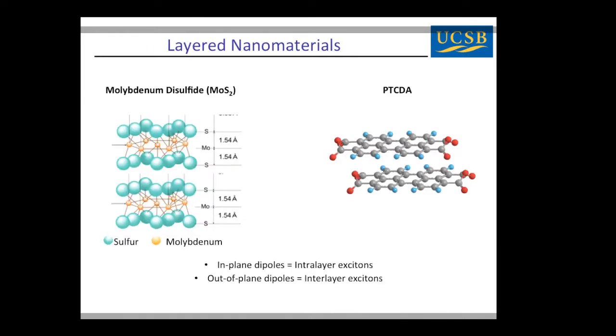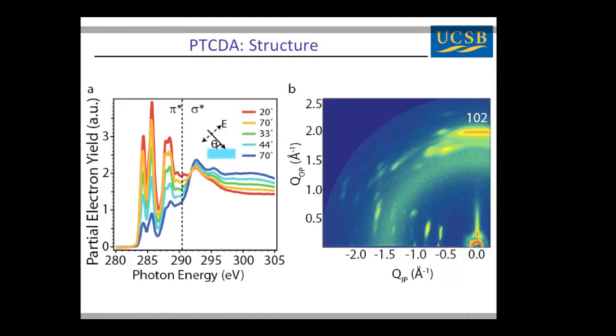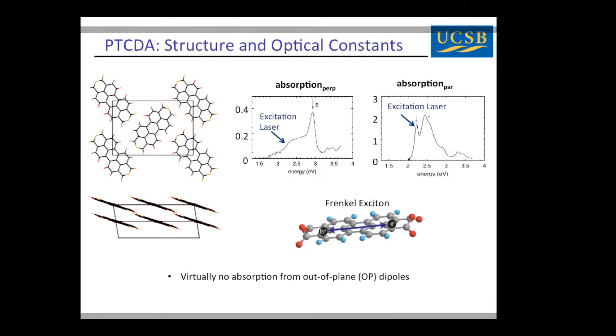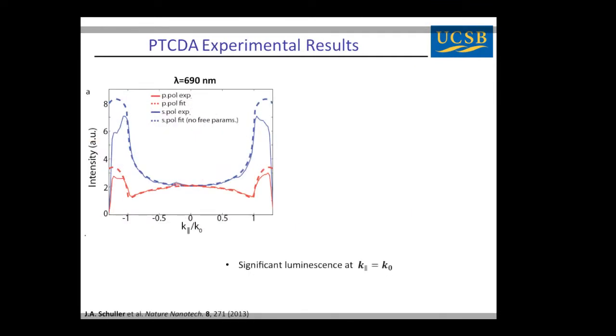So now I want to contrast that with an organic system. This is a planar molecule that, again, stacks. And now this organic molecule has much stronger interlayer interactions, okay? And so even though the absorption looks like you only have in-plane dipoles in absorption, when we look at the luminescence, it turns out that our dip no longer goes anywhere close to 0.